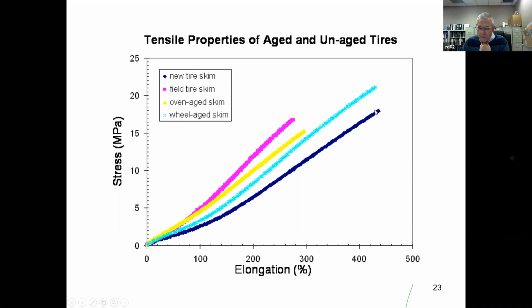So we asked the question: this is the unaged and this is the aged. If all you're doing is putting crosslinks in there, we understand the modulus going up, and we understand the elongation to break going down, but why is the strength going down? If all you do is put more crosslinks in there, it doesn't make sense that the strength is going down so much. So we spent a little bit of time trying to figure out why the strength decreased. What's the mechanism behind it?